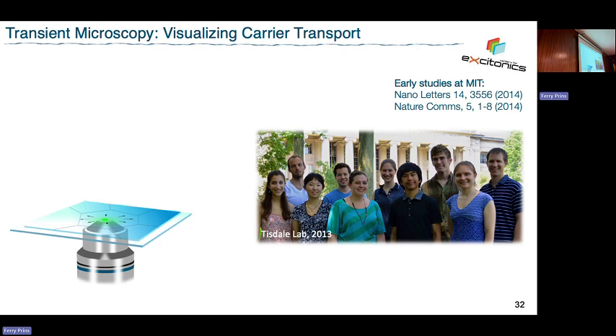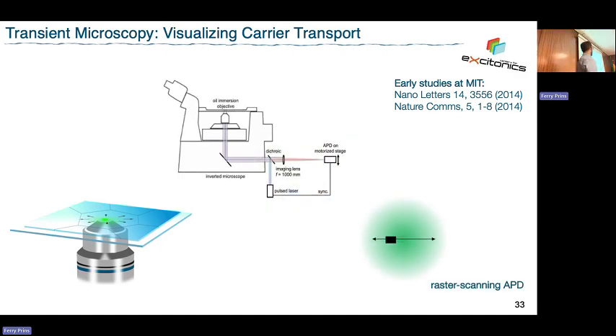And we set out to answer this question, right? To try and develop this technique. Well, this crazy idea. Is this possible? So how do we do this in practice? We take a microscope, as I mentioned, you take a pulsed excitation laser, you create this diffraction limited spot. And now you collect the fluorescence from the carriers: you create excitation, and at some point they die and emit the fluorescent photon. You collect that outside of the microscope. Now what you do outside of the microscope is you put a very large magnification, like 400 times. You use your lenses to make 400 times magnification of the emission of your population.